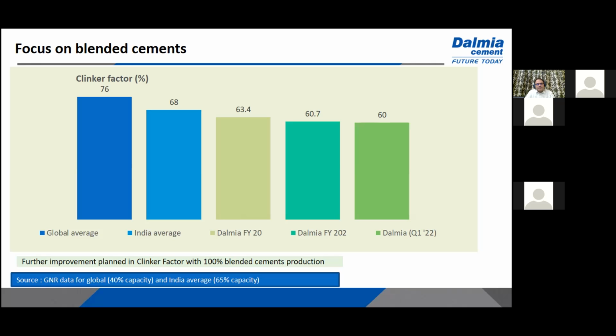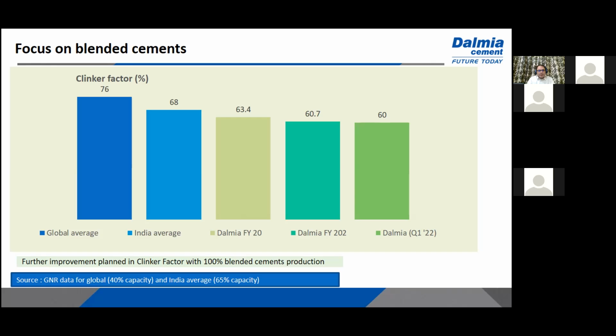When clinker is reduced, the footprint of cement is also reduced. And just to give you an idea of it, to produce 1 ton of clinker, about 860 or 870 kg of CO2 is emitted. To make 1 ton of clinker, 0.8 to 0.9 tons of CO2 is emitted. And this is the major factor from which the CO2 footprint is coming in the cement. So the less clinker we make in the cement, the lower the footprint of the cement.